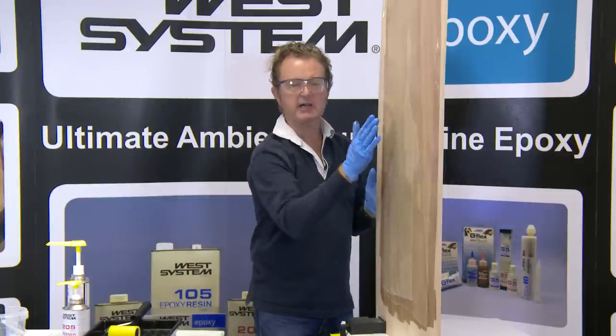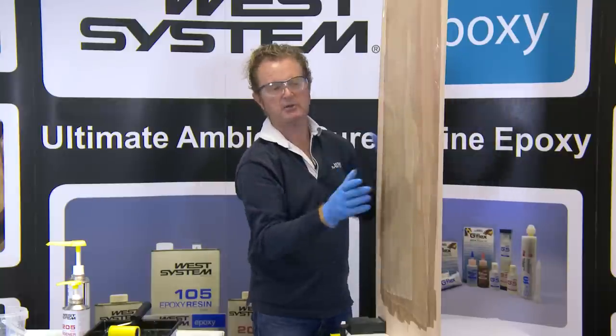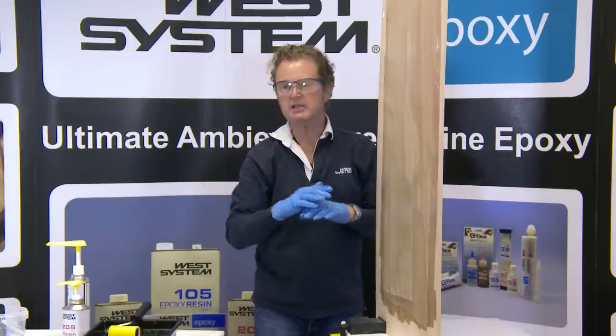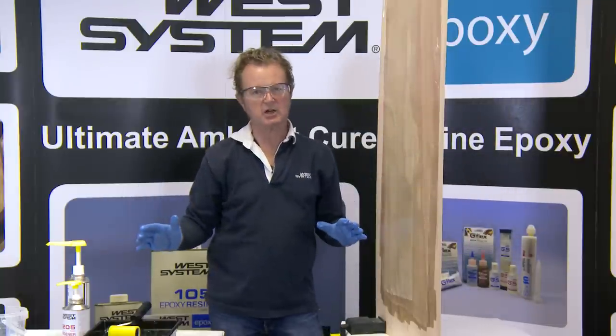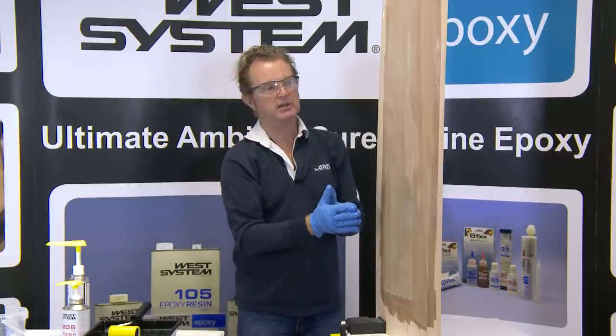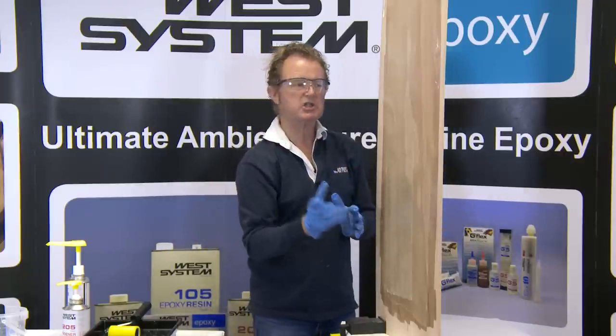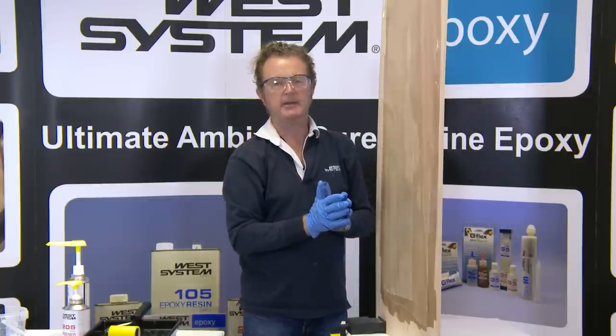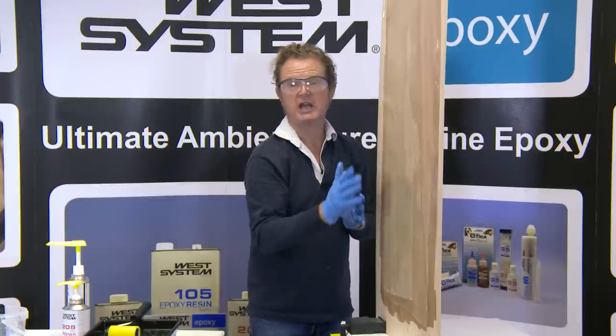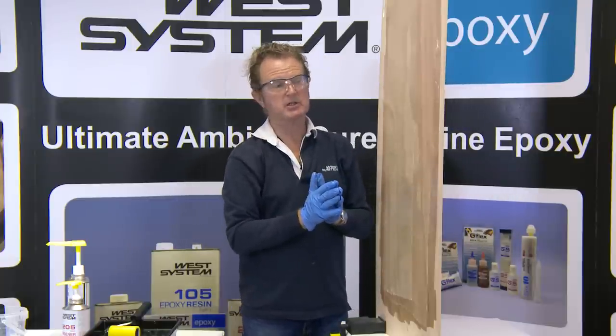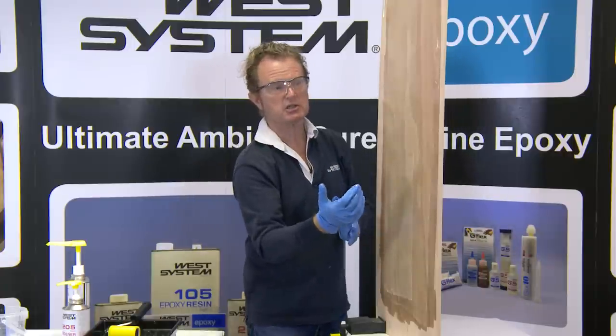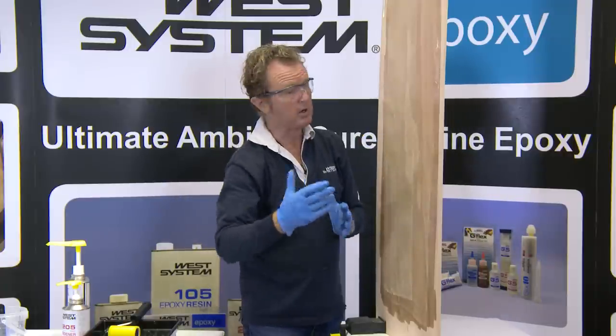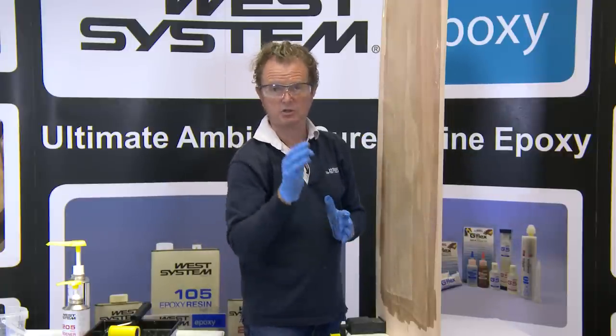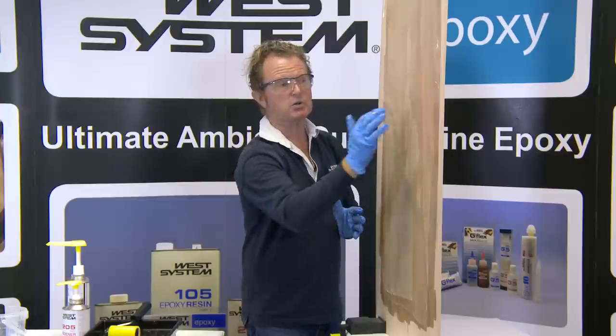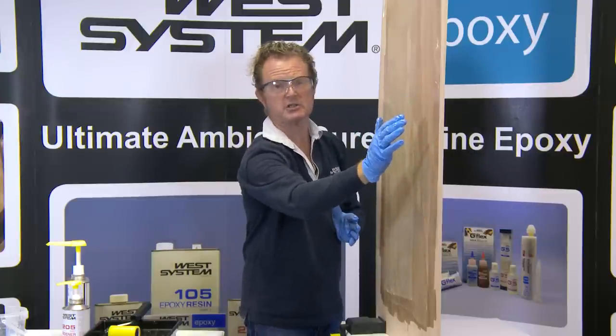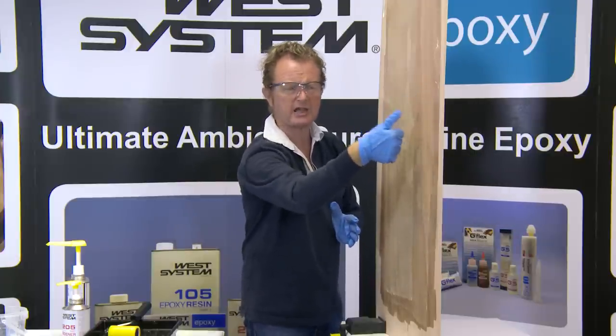Now, if I sand it, I will actually cut through some of the surface fibres, which really makes it a complete waste of time to add glass fabric. So what I want to do is a secondary process here, so that when I come to sand, I'm not sanding into the fibres. Now, for a clear finish where I'm using glass fabric, and it's quite conceivable to use glass fabric with good clear finishes, I would want to allow this to become sticky as masking tape with a surface tack on it.